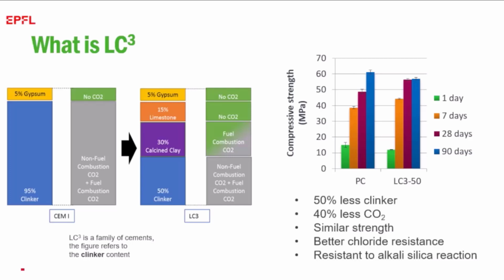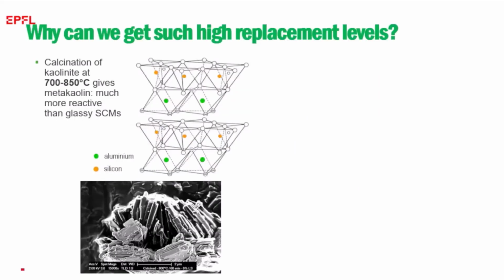So in essence, we're talking about something with 50% less clinker, 40% less CO2, because we have a little bit of energy for the calcination, and we have a similar strength, and we have a very good performance in terms of durability, in terms of resistance to chloride penetration and alkali silica reaction, which are two of the major causes of poor concrete durability. So why can we get such high levels of substitution?